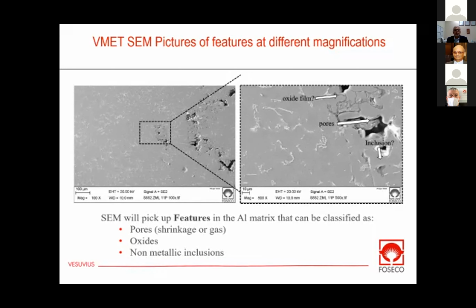So this technique enables us to identify in a given sample any pores, any oxides, any non-metallic inclusions that can lead to defects. Now, this is very important because it tells the foundry something about their melt quality. It tells, before you start casting, before you turn on your robot, you want to know how clean is my melt, how good is my melt, is my furnace ready, or is it very dirty?